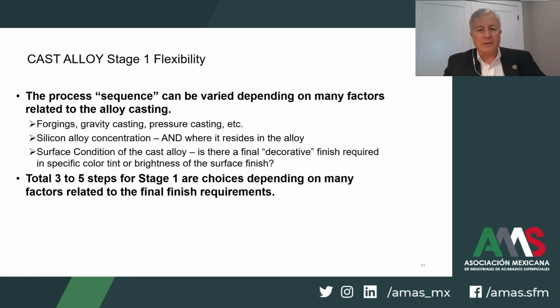The silicon concentration is one concern of cast alloys, but the type of casting process, or better stated, the method of the casting for the parts, does influence the anodizing oxide performance, which is another important variable that we have to consider. We have some data later in the webinar that will demonstrate the impact of the casting type on the performance of the oxide layer.